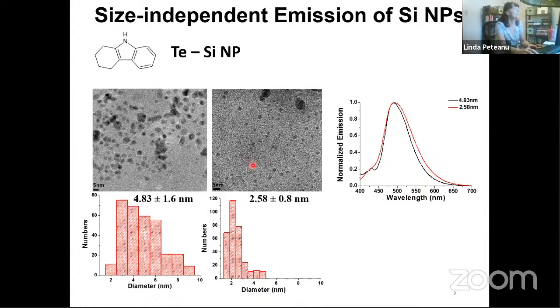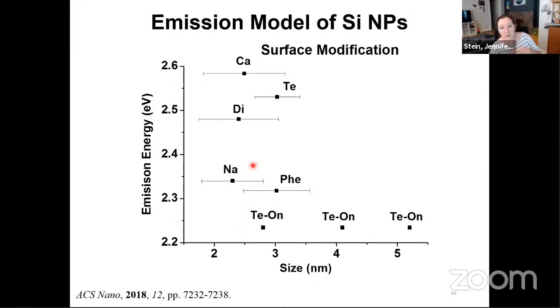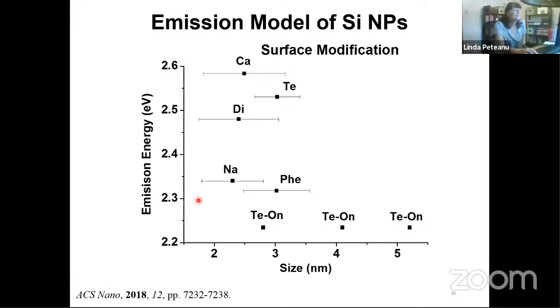So it further substantiates the need to focus on the ligand properties. Linda, what we have found, I'm sorry? I have a quick question. Sure. Those are pretty bulky ligands. Does the amount of saturation on the surface impact the quantum yield? I expect as you go to very high ligand loading, you're going to start getting some self-quenching more than anything else, because you're probably going to have ligand-ligand interactions. These tend to be on the order of about 10% of the surface. So there are a number of things on the surface, the ligand being one of them.